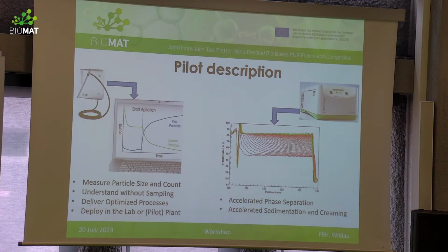And another device, LUMiSizer, allows us to control stability of the developed dispersant. Of course, it's a very important factor that you want to have a stable product. And we should not wait 3 months, half a year to determine stability. With this device, we can determine stability at different temperatures, from room temperature up to 55 degrees, with increasing sedimentation, and say in 2 hours, maximum in 3.5 days, that this dispersion is stable or not stable.